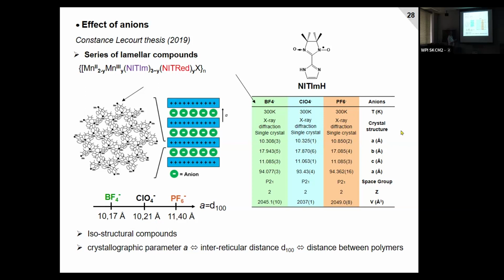So this is very, very important, because in this field, it's impossible to know the structure of organization if you have no crystal structure. And today, when you want the crystal structure, you need X-ray diffraction on single crystal. For X-ray diffraction on single crystal, you need that the crystals are big enough. Big enough means at least 50 microns. If they are less than 50 microns, you cannot do X-ray diffraction, you cannot know the crystal structure, and of course, you cannot know what your compound is. So the major problem in this field is to get the crystal structure, because to get it, you need to have a single crystal. If you have no single crystal, you cannot prove the crystal structure.